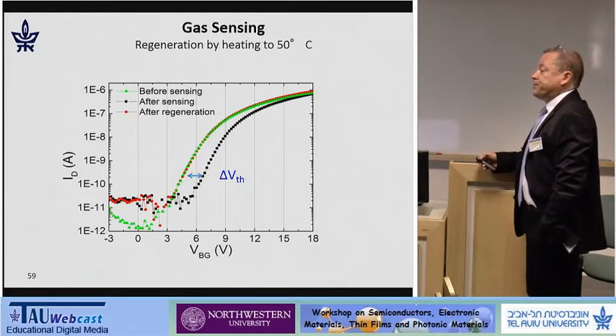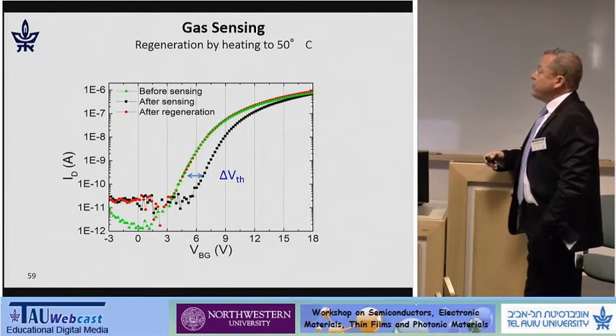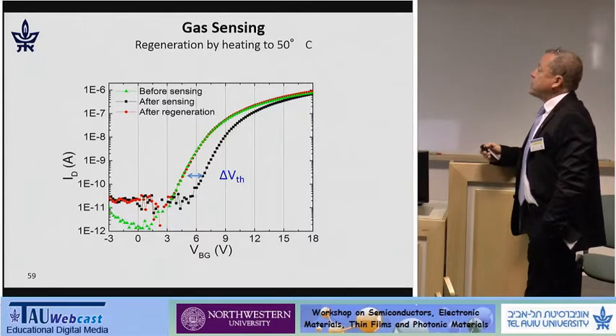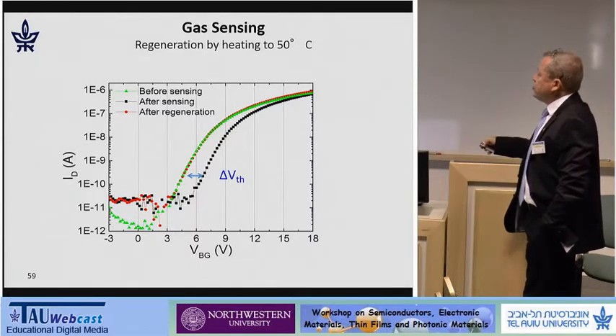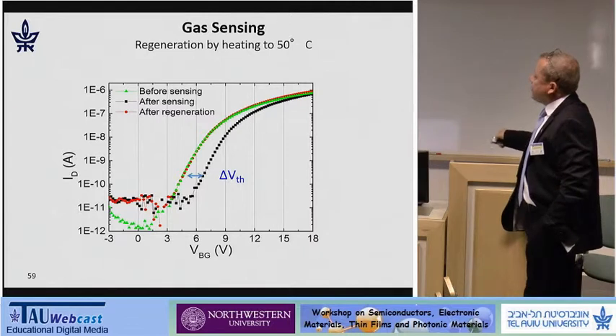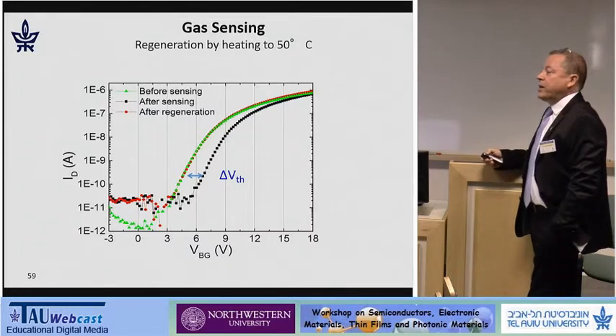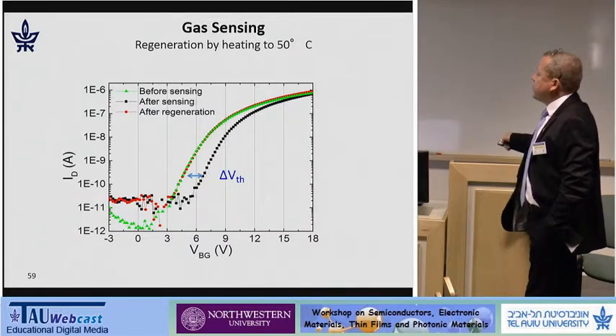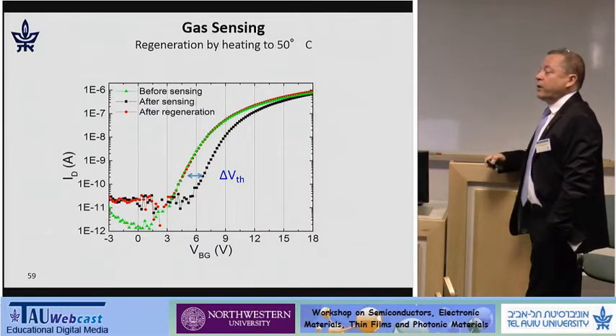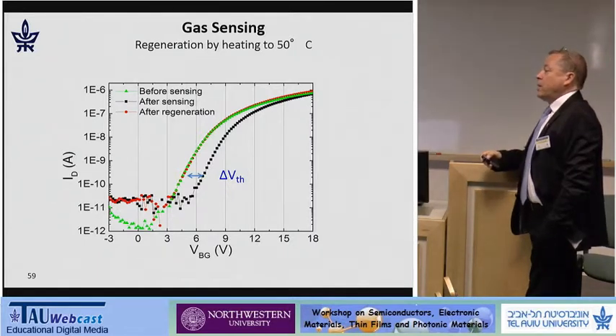Another important advantage of this device is the stability and the robustness of this device. What you see here, the green curve is the IV curve before sensing. This is after sensing of, I think, 70 ppm of ethanol, and after we regenerated with a gentle heating to 50 degrees, the curve comes exactly back to the original one. This is very important and fairly hard to achieve with conventional nanowires.